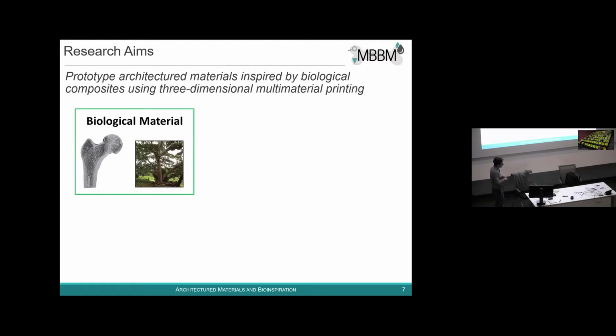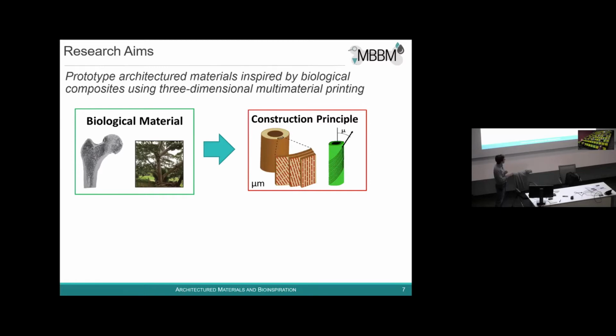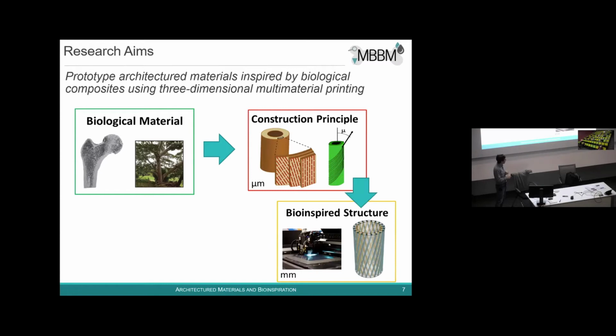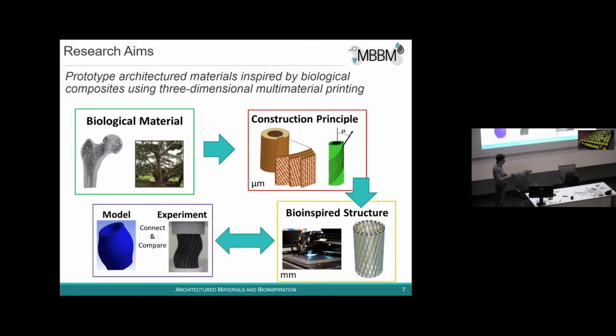So the idea is that we start from an observation of a construction principle of a biological material. We focused a lot on bone and on wood. And then we isolate the construction principle, which is typically at a small length scale, as I said, intermediate between nanometers and millimeters. And then we scale this up. We simplify this, and we decide which features we want to replicate. We use three-dimensional printing. And at the end, we use experiments and computer simulation to understand if these construction principles are also working in artificial materials, and to see the constraints and the advantages that this is bringing to the bioinspired structure. So that's the research strategy that we are following.